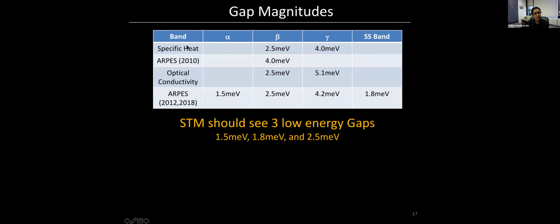And if you take data from specific heat, ARPES, optical conductivity, etc., and you put it all together, basically you find that these two hole pockets are expected to have a gap of approximately 1.5 meV and 2.5 meV. And what I talked about earlier, which is the topological surface state, is expected to have a gap of 1.8 meV. So leaving aside this larger gap, if you look at the energy range between 1 and 3 millivolts, what you should see with STM is actually 3 distinct coherence peaks associated with these 3 bands, 2 of which are the bulk bands, and 1 of which, this one, is the surface state.